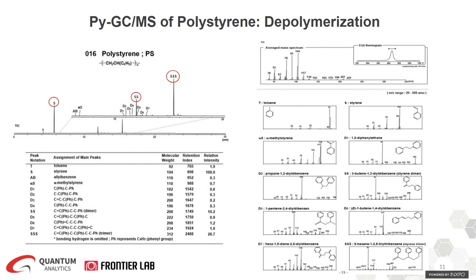So this is an example that shows the flash pyrolysis or PyGCMS of polystyrene. And as I noted, polystyrene goes through a depolymerization mechanism. So you're able to see the starting monomer, dimer, and also the trimer. So as shown here from the book, you can see the pyrogram on the top from the left side, and then the assignment of main peaks, as well as the average mass spectrum that is shown on the top right side, and the EGA thermogram. And also you could see some of the major pyrolyzates or fragmentation of the polymer.